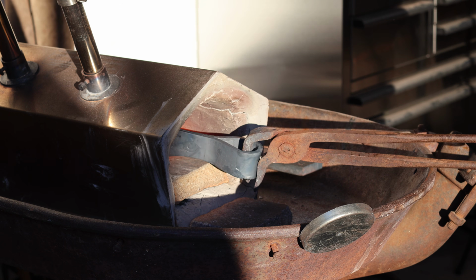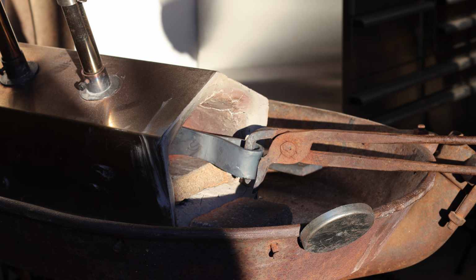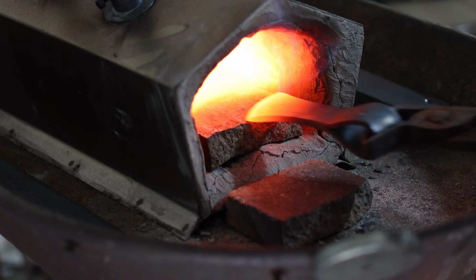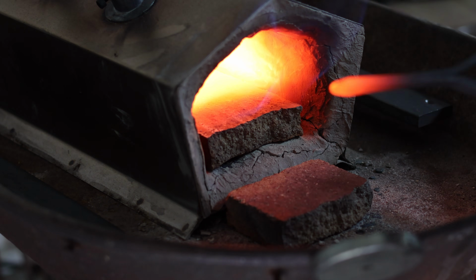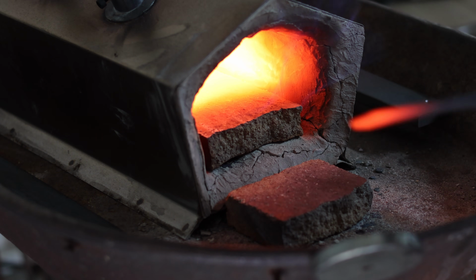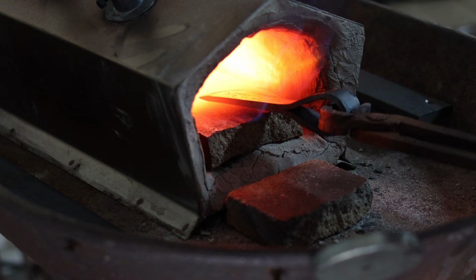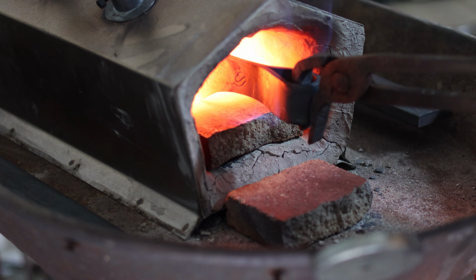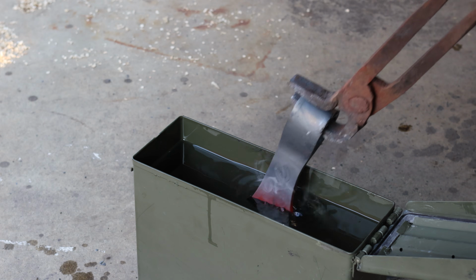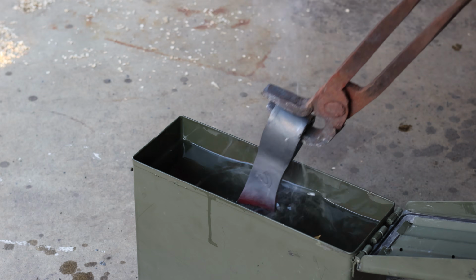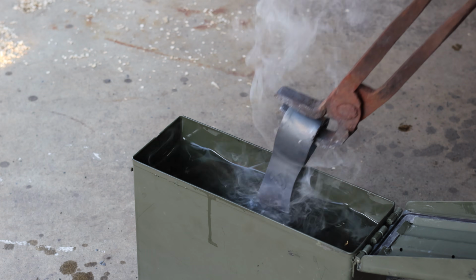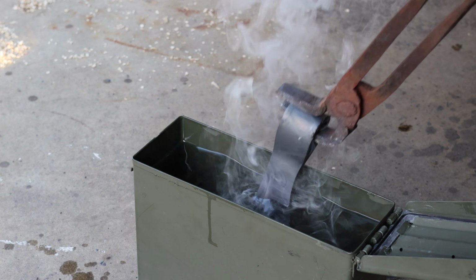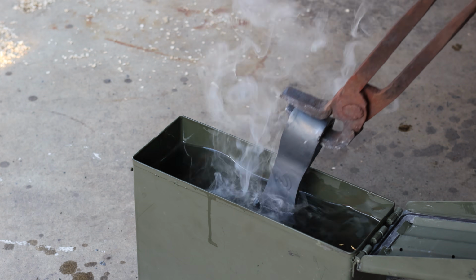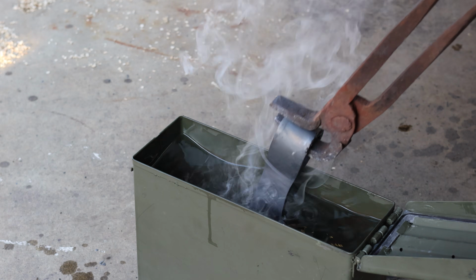So we're gonna bring this up nice and slow in my forge. I'm gonna be placing a magnet on the tray of my forge so that I can make sure that it reaches non-magnetic. I wanna get it a little hotter than that non-magnetic temperature, and then I will quench it in some preheated mineral oil that I've got in this ammo can. And this oil is preheated to about 130 degrees just by quenching different pieces of mild steel to get it hot enough.